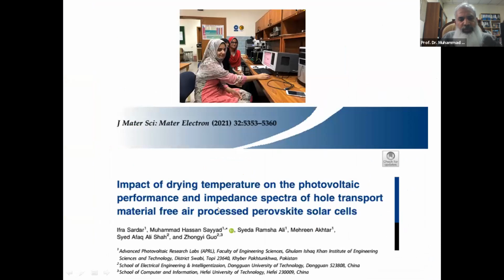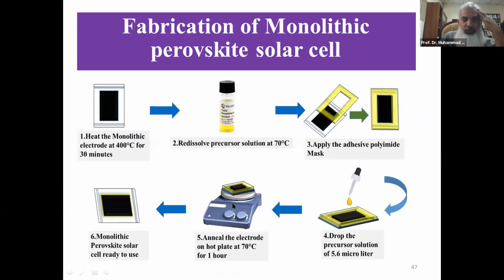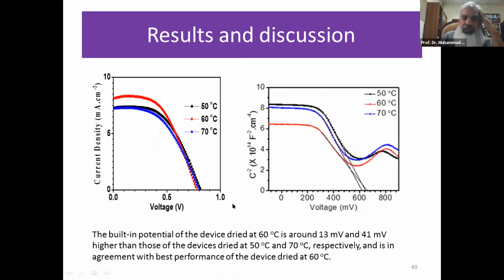And the paper has been published recently about the impact of drying temperature on photovoltaic performance and impedance spectroscopy of hole transport material free air processed perovskite solar cell. It was done as part of MS thesis of my students. And these are the results. You can see from the IV data that at 60 degrees, the performance is highest.